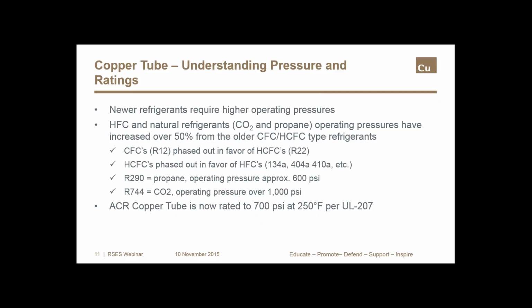Copper tubes and fittings are well suited for new refrigerants with higher operating pressures. ACR tube is rated to 700 psi at 250 degrees Fahrenheit, and this is certified by UL 207. But manufacturers are actively promoting new products for high pressures. And we'll talk a little bit later about copper tube for extra high pressure applications.